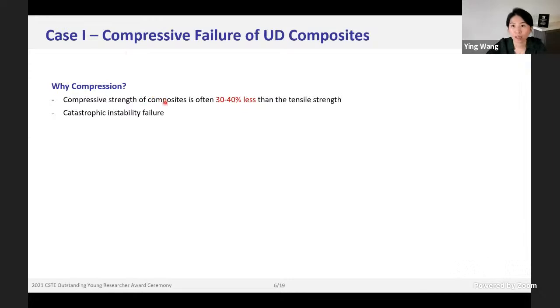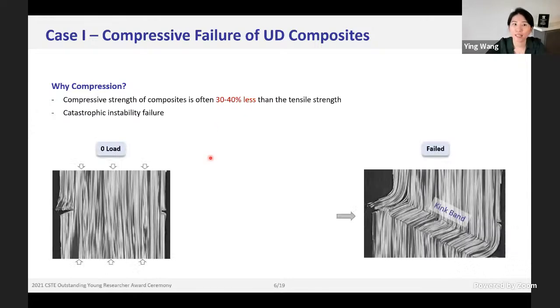So why do we study compression? Compression is really a classic problem in composite study. It's because the compressive failure of composites is often 30 to 40% lower than its tensile strength. And the other fact is that compression failure is always associated with the development of kink bands, which makes it a catastrophic instability failure, and it's difficult to characterize experimentally. Could you imagine, at 99.9% of the failure load, just prior to failure, what will the composite look like?